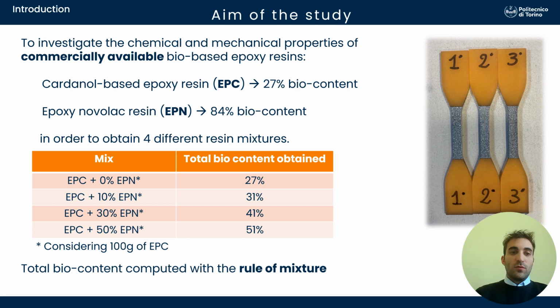In our study, we wanted to investigate the chemical and mechanical properties of two commercially available bio-based epoxy resins characterized by two different biocontent, in order to obtain 4 different resin mixtures by mixing them together. In particular, we wanted to mix an epoxy novolac resin with a very high biocontent with cardanol-based epoxy resins with different weight percentages, as you can see from the table. And we obtained 4 different total biocontent, which were computed by means of the rule of mixtures.